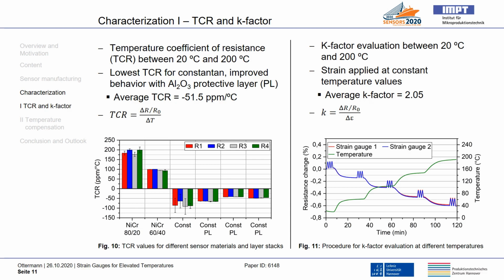Out of these resistance changes, the K-factor can be calculated according to this formula, which is analogous to the TCR formula, but this time the strain appears instead of the temperature. The result is an average K-factor of 2.05, which is independent from the temperature.